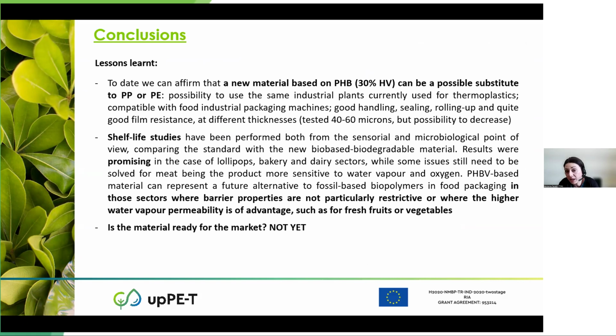We tested so far thicknesses around 40-60 microns. But as you know, the current solutions on the market are around 30 microns. But for sure, there is some space for improving. In terms of shelf life studies, we perform both sensorial and microbiological tests. And the results were promising in the case of lollipops, bakery, and dairy sectors, while some issues still need to be solved for meat, being the product more sensitive to water vapor and oxygen.